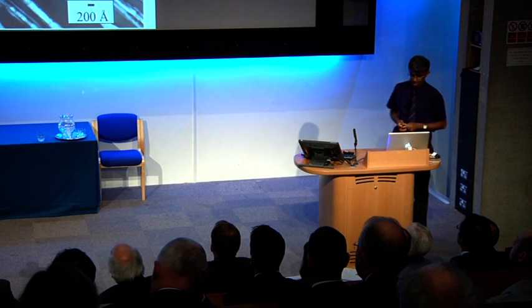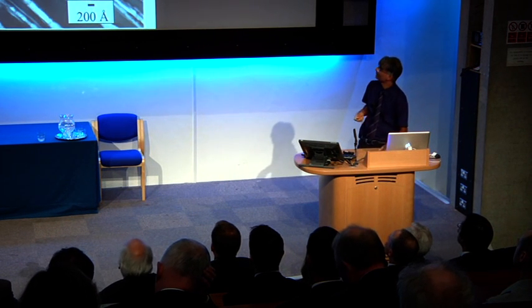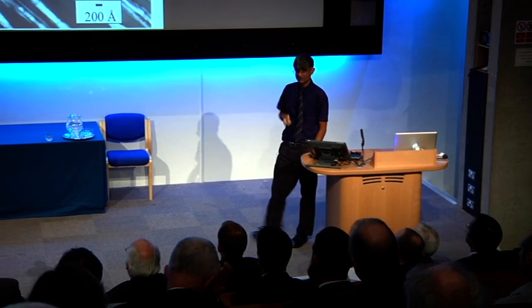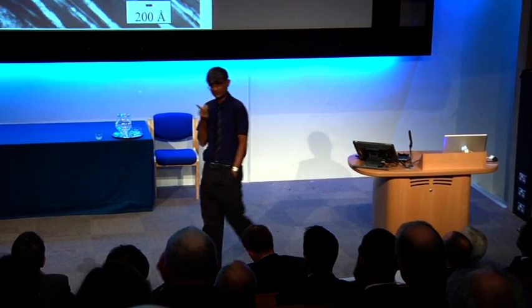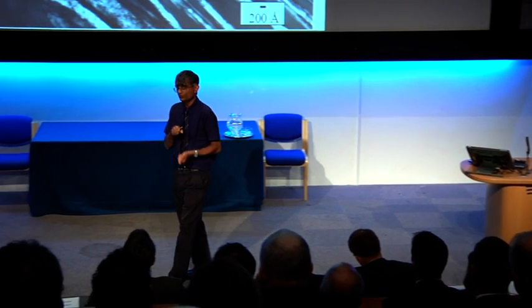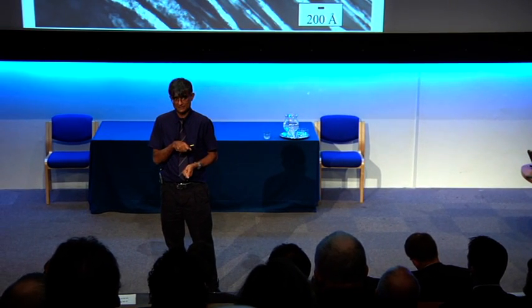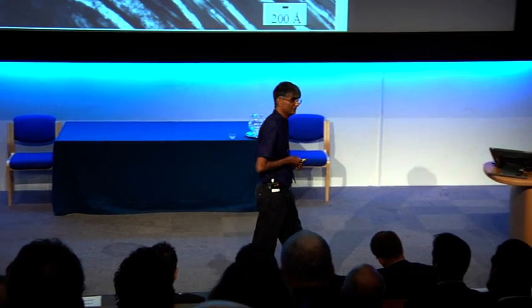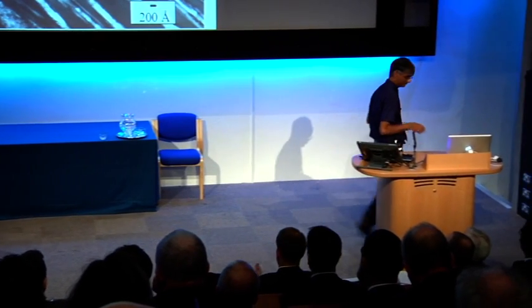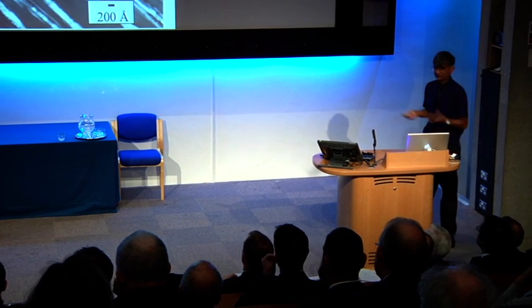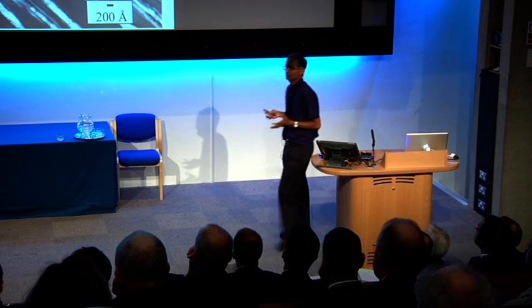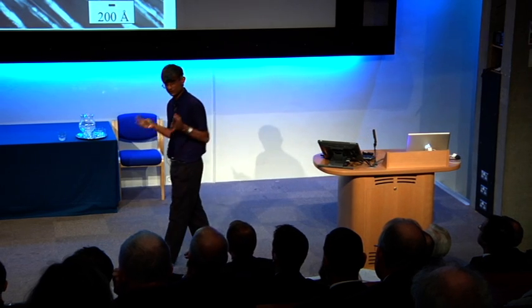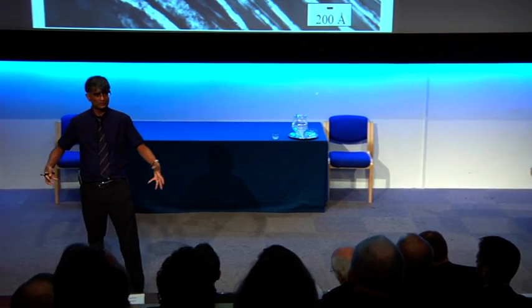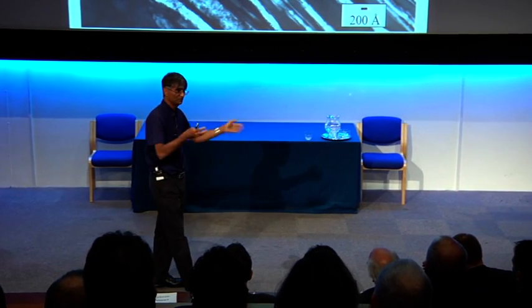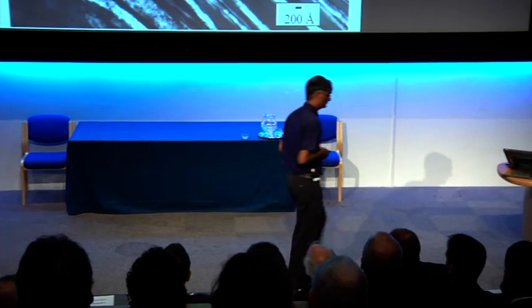So let me just summarize. This is our structure. It's very strong. It has uniform ductility. If you look at the standard bearing steel, you have to do the tensile test very carefully to detect plastic strain. Here we can get between 7% and 30% of plasticity. It doesn't require deformation to produce this structure. It doesn't require rapid heat treatment, which is a big advantage if you look at things like distortion. Okay. And therefore you're not left with a system of stresses inside the material before you actually do anything with it.